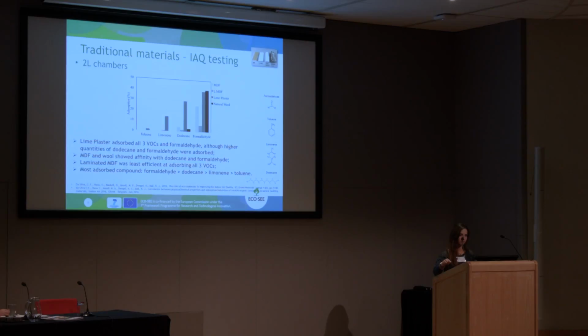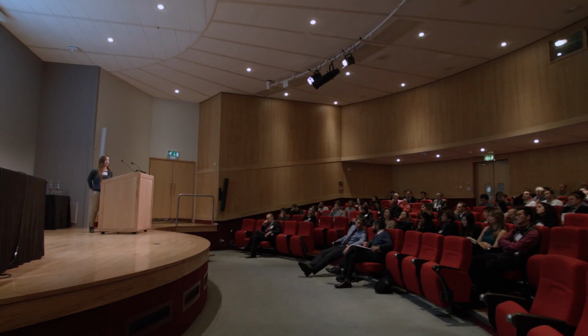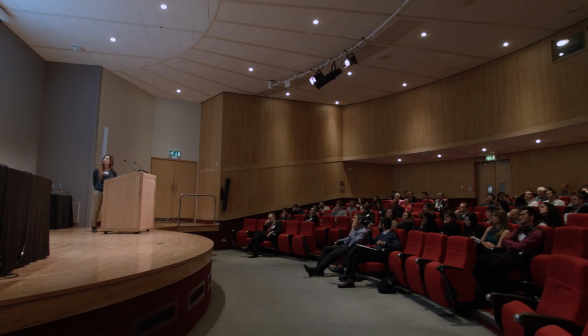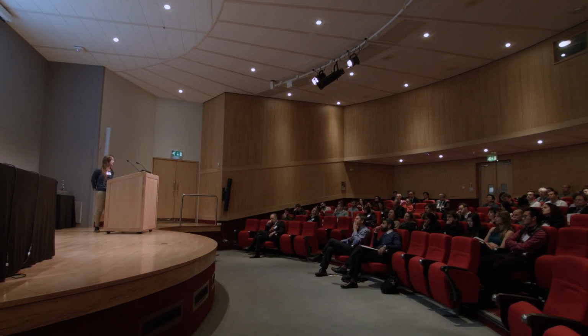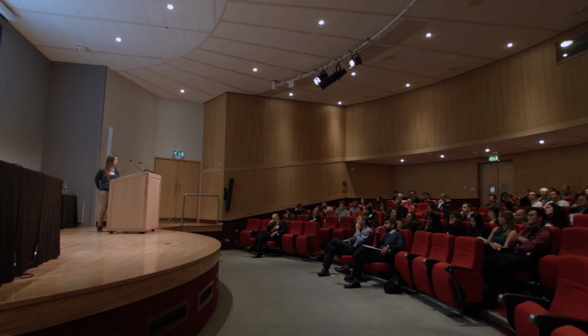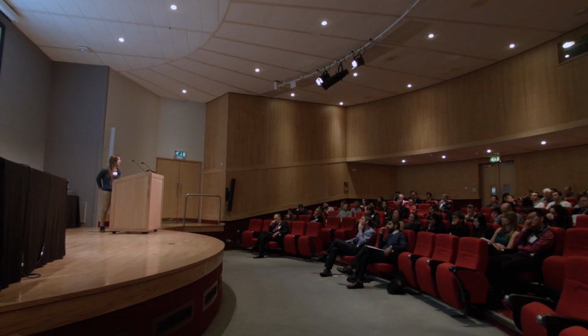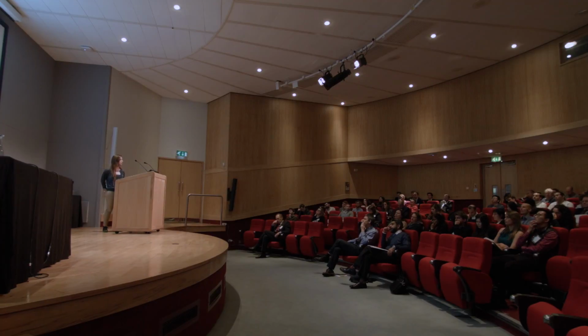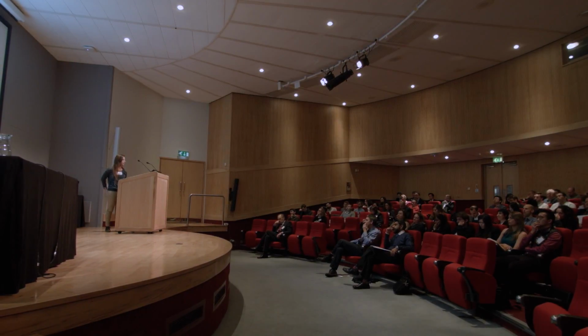This graph shows a bit better how these four materials were performing in the adsorption-desorption experiments. We can see the lime plaster was the material that adsorbed all four VOCs the most, and natural wool performed well with the formaldehyde. This is because of the proteins in the composition of natural wool, which react with formaldehyde by chemisorption.